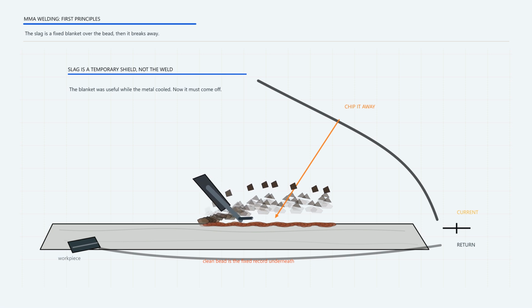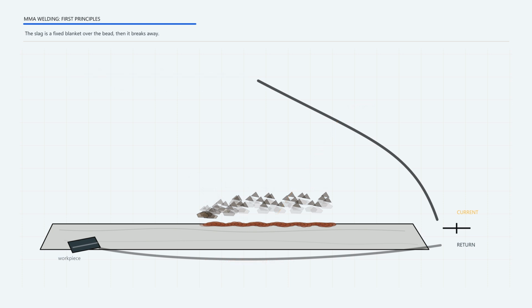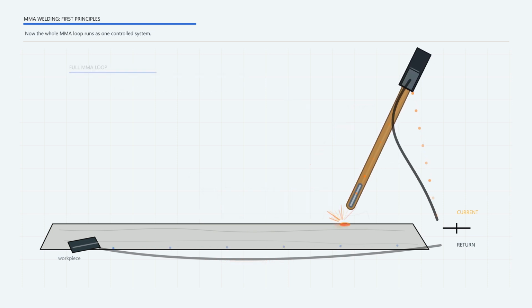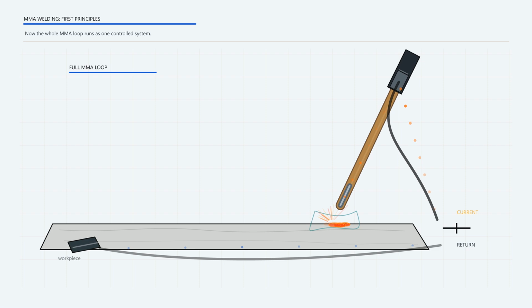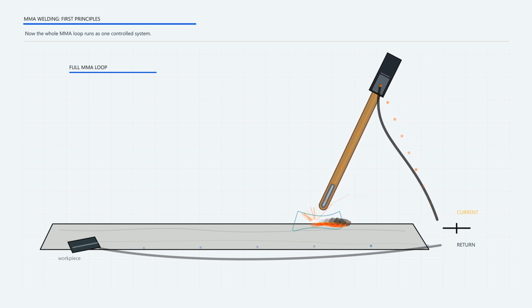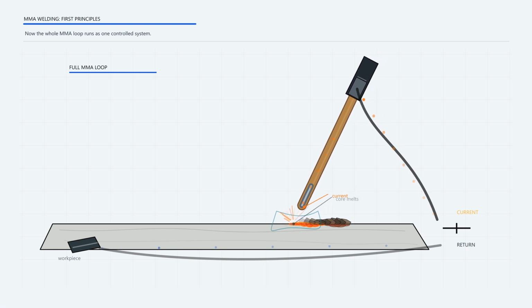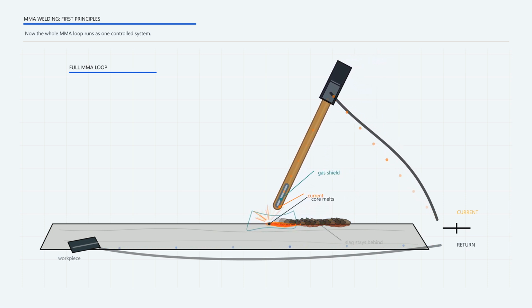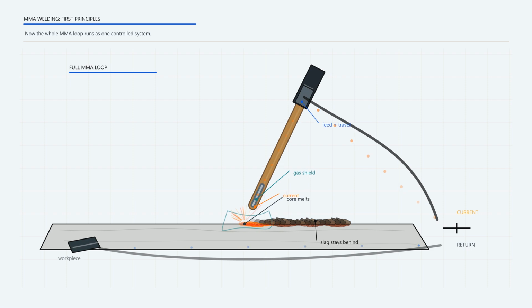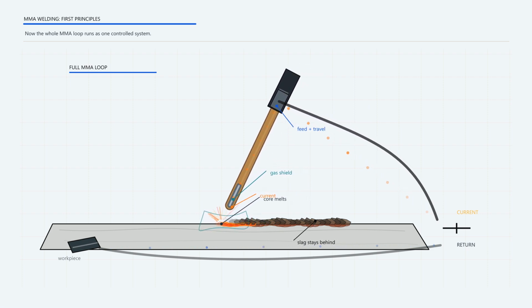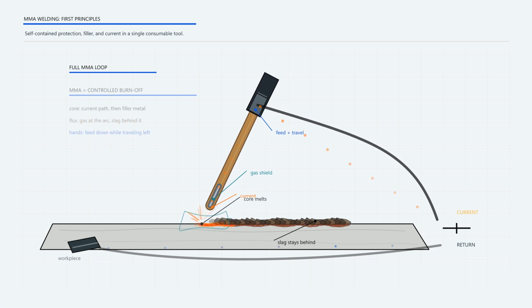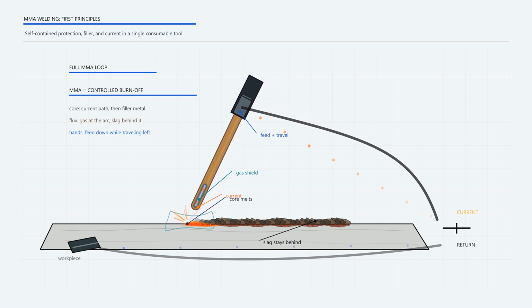Now watch the whole system again. The return clamp is connected. Current runs through the holder and the coated rod. The arc melts the core into the pool. Flux makes gas at the front and slag behind it. The rod shortens, the hand feeds down, travel carries the pool forward, and the cooling bead waits under its temporary shield. That is manual metal arc welding in first principles. One coated consumable rod carrying heat, filler, shielding, slag, and control into one molten point.